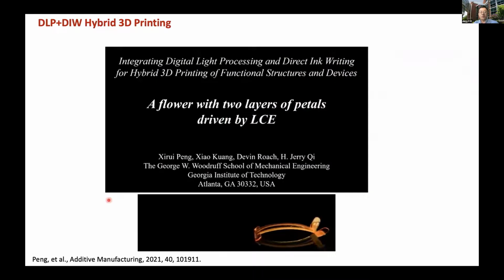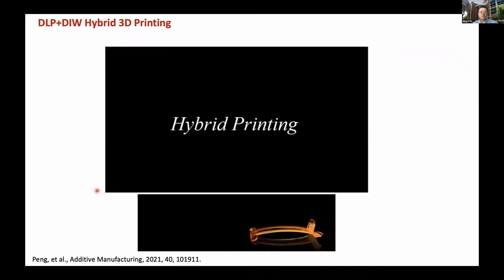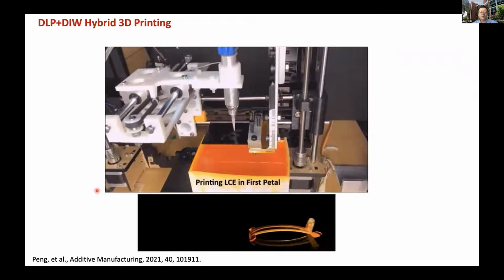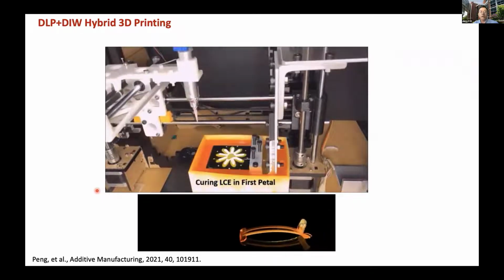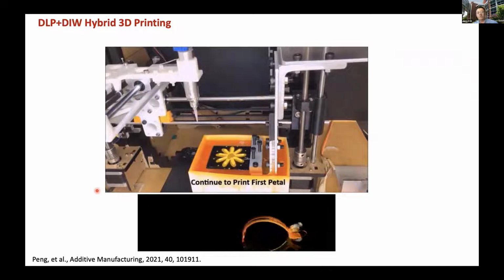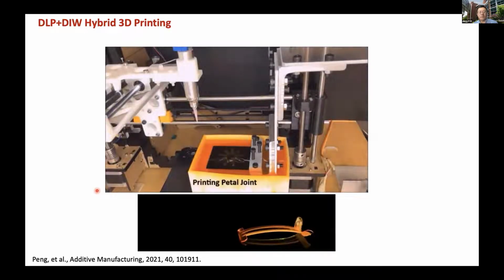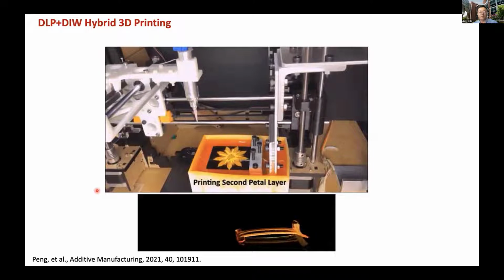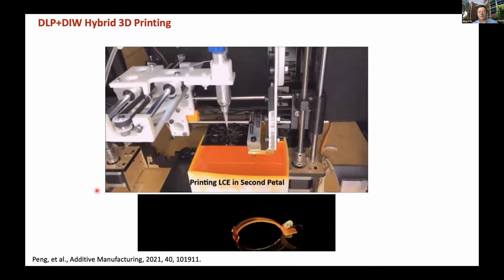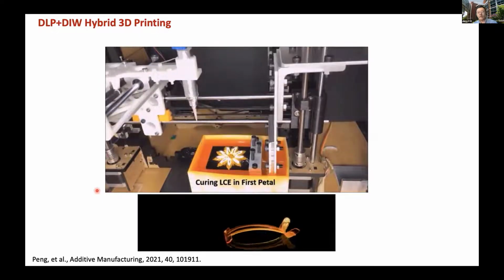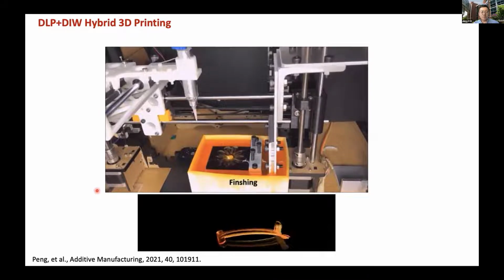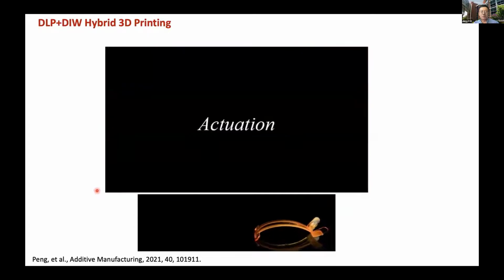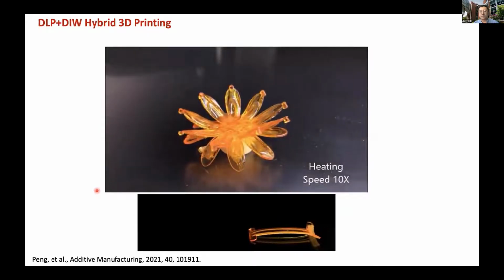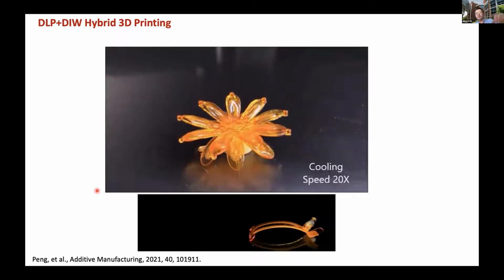Here the video shows how we print these flower structures. We first print LCE on the bottom. You can see we're writing the LCE on the bottom. And then we put it into the liquid reservoir for the photopolymers, and here we shine the lights. We can print the structures of the flower petals using the DLP. And now we're trying to print the next layer. Then we can take it out and print another layer of LCE on the top, and the speed is accelerated in the video. After printing, you take it out and you can see the actuation. This one has LCE inside, so you just heat it up and you see the flower move.